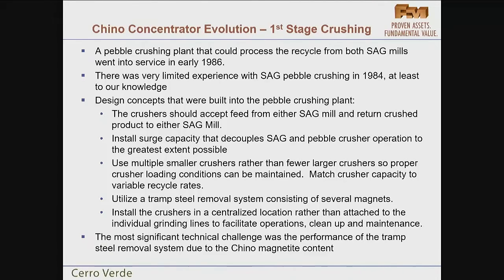So we wanted the crushers to be able to accept feed from either SAG mill and return it to either SAG mill. Flexibility. Install some surge capacity to decouple the SAG and pebble crushers. Decoupling is very important. More flexibility: use multiple smaller crushers rather than a few big ones or one big one, so you can match the equipment capacity to the processing rates required. It is important to have a very good tramp steel removal system, and install the crushers in a centralized location rather than attached to individual grinding lines where there's absolutely no flexibility.